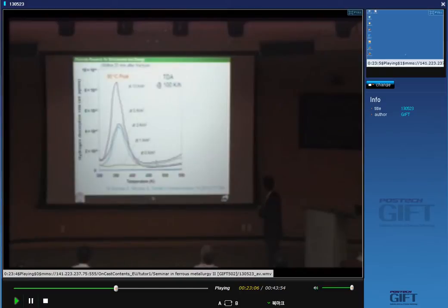We did TDA analysis at the heating rate of 100 Kelvin per hour with conditions of 0, 1, 3, 5, and 10 ampere per square meter. You can see the 90 degrees C peak almost constant for all conditions. We did this one within 20 minutes after fracture.